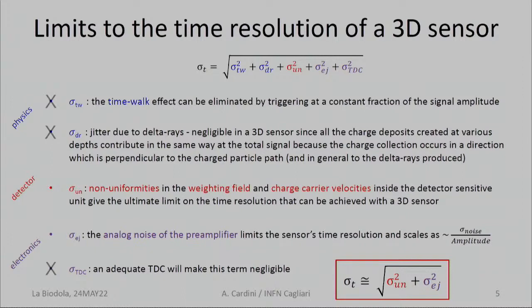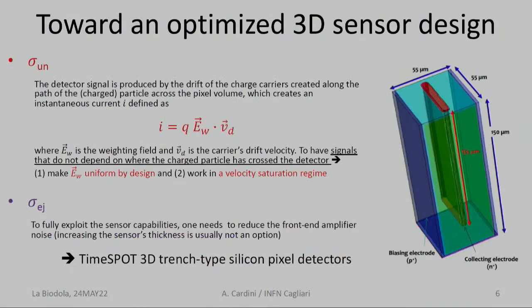So at the end we are left with two components: the non-uniformity of the sensor itself and the electronic noise. We have come to a design where, by using these trenches, we try to make the weighting field as uniform as possible by design, and to work in a velocity saturation regime of the charge carrier so that as much as possible all the signals will be identical to each other. Still, we will have this part, which is the noise of the front end.